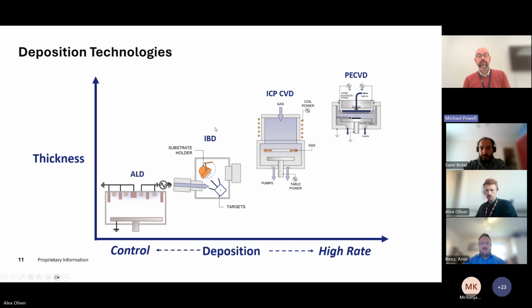But if you wanted really fast rate, you would go towards our CVD side. Chemical vapor deposition is a very fast rate process. With plasma enhanced CVD, you can get thousands of nanometers a minute. You'll never get that in ALD, but in ALD we can give you processes that can be hundreds of nanometers an hour, so you still can get throughput, but that means you get the control, so you're able to better control. Next slide, please.